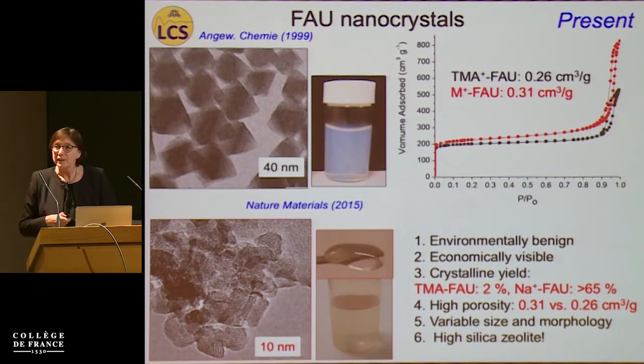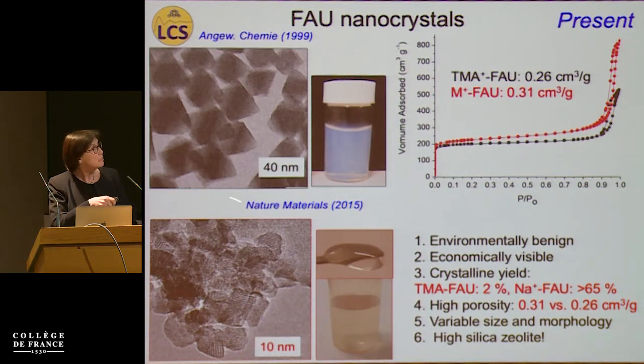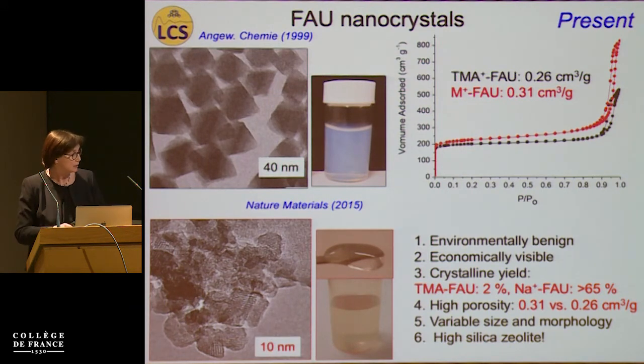Here is an example of how faujasite nanocrystals synthesized 20 years ago in the presence of organic template appear, in comparison with the nanocrystals synthesized free of organic template, just in the presence of sodium. As you can see, we were able to decrease the size from 40 to 10 nanometers. We were able to increase the crystalline yield from 2% to 65%, and also the crystals synthesized free of organic structural directing agents have better micropore volume, and the lower micropore volume for the templated crystals we explain with the partial collapse of the crystalline structure during calcination.